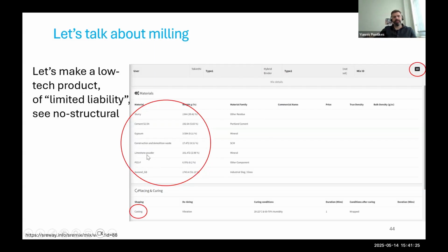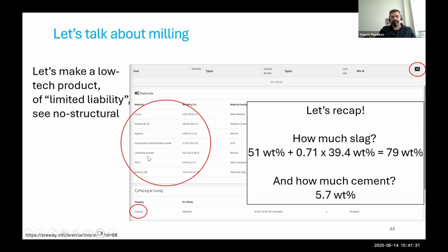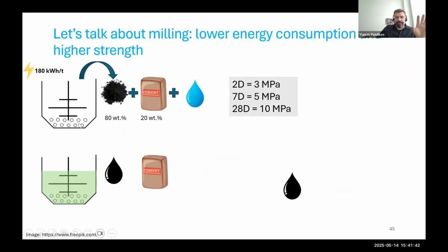So we've done the milling, and then we've done casting, okay? And why do we do that? Because we want to make an easy process. So if you now think of the slag component, it's about 80 weight %, and the cement is about 6%, which I think is quite attractive. Again, how we do it, we did it.